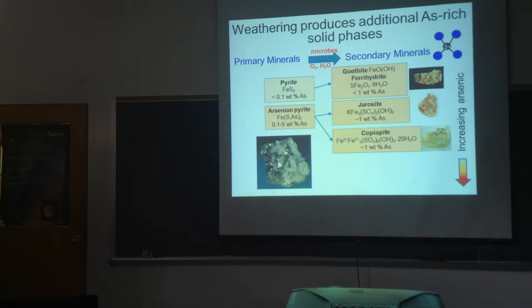There are some additional minerals that tend to be weathering products of the original primary ore minerals when you get into the higher arsenic form. Jarosite, which is a potassium ferric sulfate, can have about 1% arsenic, and again, the arsenic substitutes for sulfur, but now it's in the oxidized form, arsenate, substituting for sulfate. And then copiapite is another sulfate mineral with both ferrous and ferric iron, and you can also have a small amount of arsenic substituting for the sulfur in copiapite.